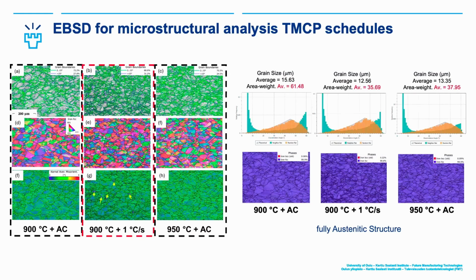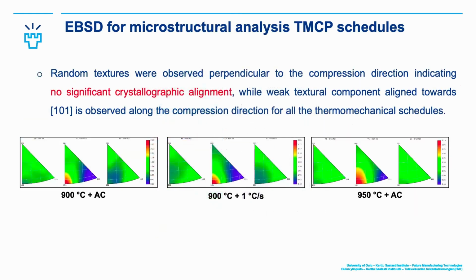So this could explain why we have lower hardness for this specific case. Also, we had the average grain size, and just to mention that this is still fully austenitic out of this TMCP sample, despite those small fractions of 0.06, so maybe kind of error. And for the texture, it was random textured except for the y direction, which actually is the compression direction, because of the pancakes, so there is this effect.